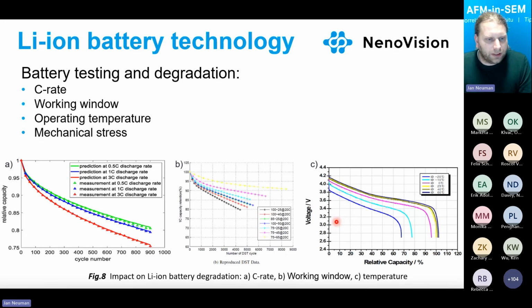Batteries are usually tested by long-term cycling. We can cycle them at different C-rates. It means the current which we apply for charging and discharging can be set to a different rate, so the battery can be charged and discharged faster or slower. If we discharge the battery faster, like the red curve in picture A, you can see that if the rate is higher, the degradation is also higher, and the capacity decreases faster.